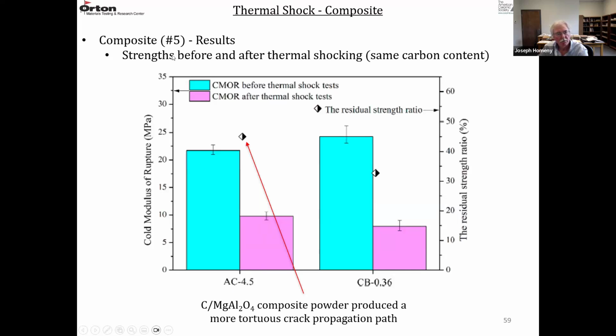So this is the before and after strengths for thermal shocking of AC 4.5, which we said had the optimum behavior for thermal shock, against this one, CB-0.36. So this has no carbon spinel powder additions, but it has the nanocarbon black addition at 0.3%, 0.36%. And if you look at the residual strengths here, the AC 4.5 had a better residual strength retention.